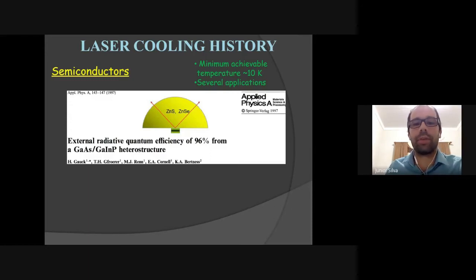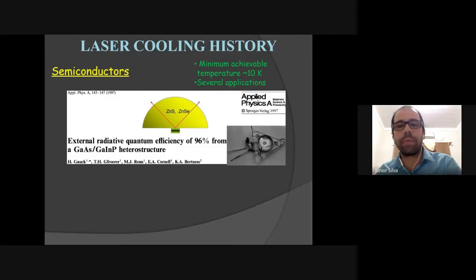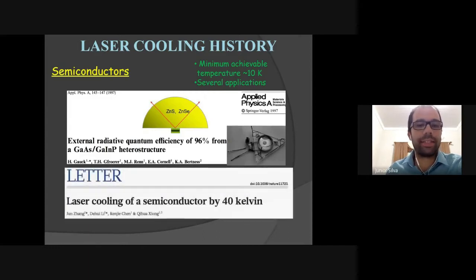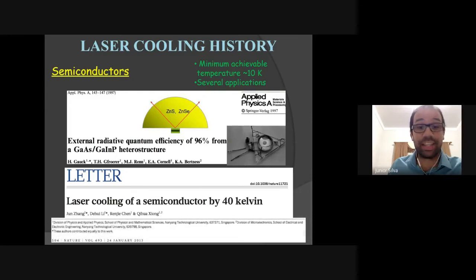Okay, here we can see another picture, a real picture. This one, a real picture. They need to put this dome lens on the material because the refractive index is so different from the air that the luminescence cannot escape. So you use the dome lens only to make the luminescence escape the material. But after this, in 2013, some researchers from, let me remember, I think it's the next, if you click one more, from Singapore, yes. These guys claimed to have observed the laser cooling effect in a semiconductor, cadmium sulfide. But they could not reproduce this experiment, and nowadays they have been very criticized by other researchers.